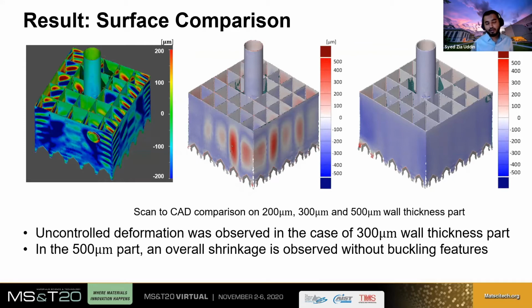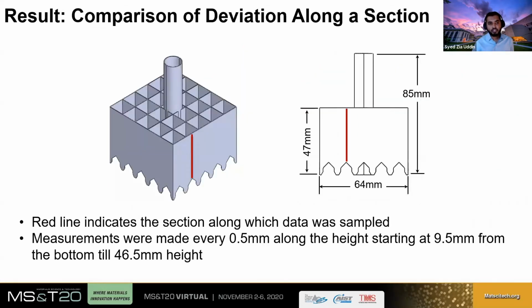Some overall comments on this plot: we see a bluish color in the contour plots, which indicates an overall shrinkage of the parts, which is very typical of the laser powder bed fusion process. We see some alternating red and blue colors, which indicates in and out of plane deformation, which we are calling buckling here, of these thin wall structures. Then in the next few slides, we'll take a look at some particular measurements of deviation along a section we choose.